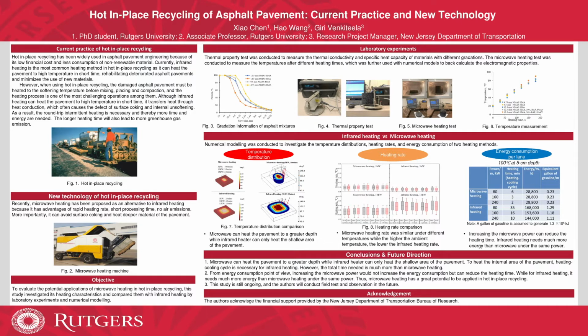And from the energy consumption point of view, increasing the microwave power would not increase the energy consumption, but can reduce the heating time. While for infrared heating, it needs much more energy than microwave heating under the same power. So the microwave shows a great potential to be applied in hot in-place recycling. And this study is still ongoing. The authors will conduct field tests and observation in the future by using microwave and infrared heating.